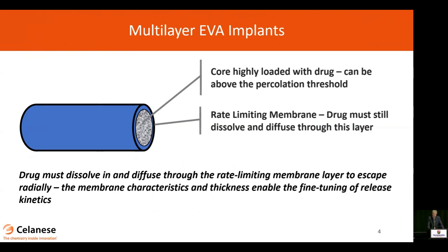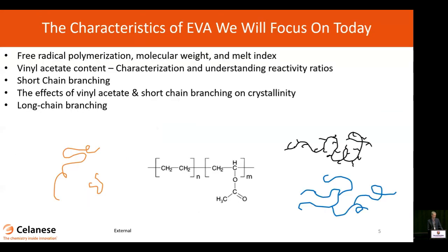So in a system like this, you typically will have a core that's highly loaded with drug, right? And that core is EVA plus drug. And then it's surrounded by some sort of rate controlling second layer that functions as a membrane. And so you actually can manipulate the release characteristics of a device like this by adjusting parameters such as the thickness of that outer membrane, as well as aspects of the chemistry characteristics of the polymer that's used in that membrane.